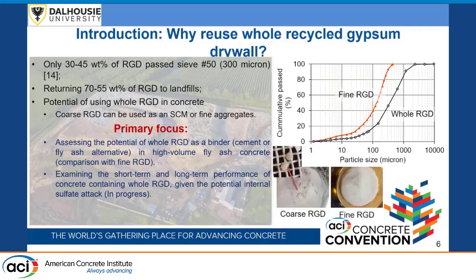And we know that because of the recycling loop, the RGD has a potential to be used as SCM and fine aggregates in the concrete. We use both, but in this presentation, I just go with the SCM. So the primary focus of this study is assessing the potential of whole recycled gypsum as a binder, either cement or fly ash alternative in high volume fly ash concrete, and compare the result with the fine recycled gypsum drywall. I also go to briefly explain our in-progress research on the short-term and long-term performance if I have time.